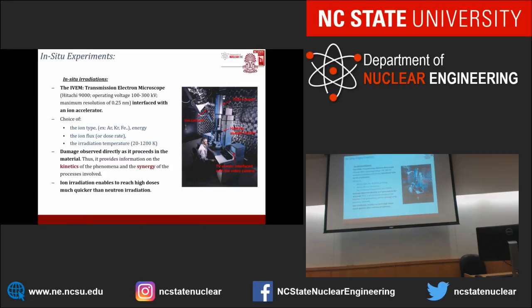So we performed in situ ion irradiation experiments at the IVEM facility at the Argonne National Lab. This facility houses a transmission electron microscope, which is interfaced with an ion accelerator. The transmission electron microscope is a very powerful tool for characterizing the microstructure at the atomic level. The combination of the ion accelerator with the microscope allows us to introduce radiation damage into the material and meanwhile observe the evolution of this damage during the irradiation. This kind of experiment provides information on the kinetics of the phenomena that occur under irradiation.